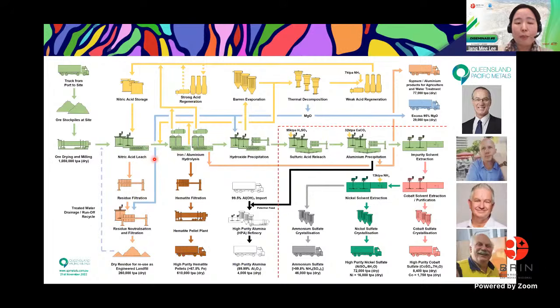The beauty of this flow sheet is that we can recycle the nitric acid solution, and this will be fed back to the fresh nitric acid leach. Nitric acid is more expensive compared to sulfuric acid, but in this flow sheet, we recycle the nitric acid and make a closed loop when we extract the critical metals from the laterite ore.